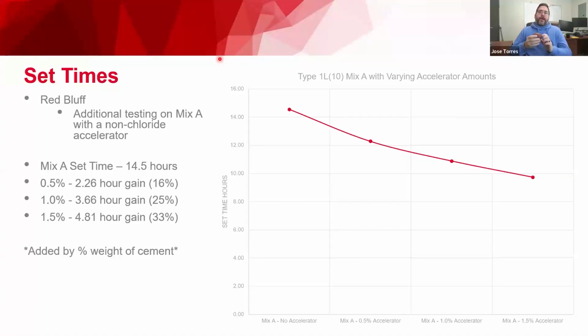We saw that for our mix A at Red Bluff, which had an initial set time of 14.5 hours, we were able to get some set time gains by adding varying amounts of accelerator. At 0.5%, we gained 2.2 hours. At 1%, we gained 3.6 hours. And at 1.5%, we gained 4.8 hours. So quite a bit of gain with the use of the accelerator, but we do start seeing some diminishing returns as we add more.